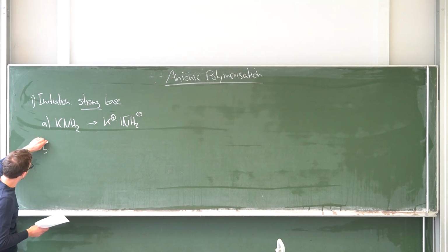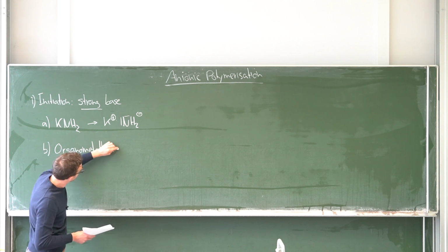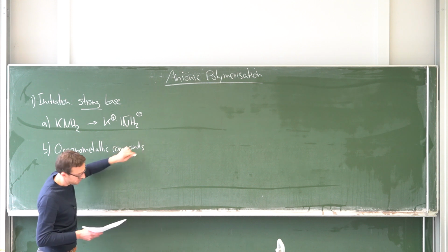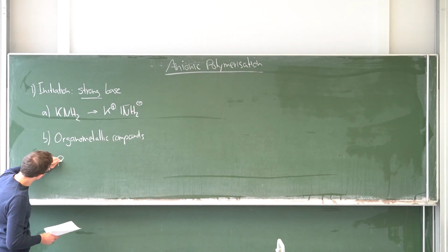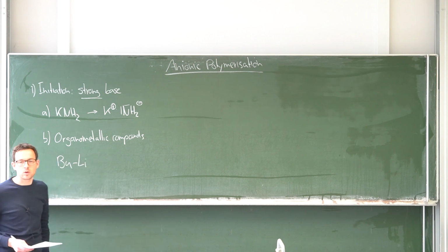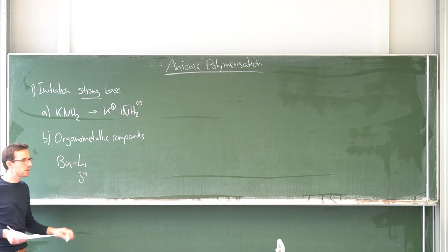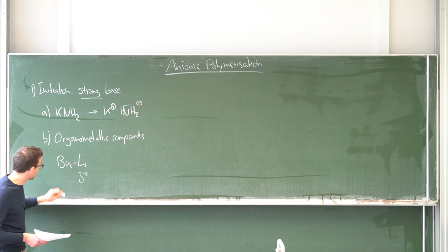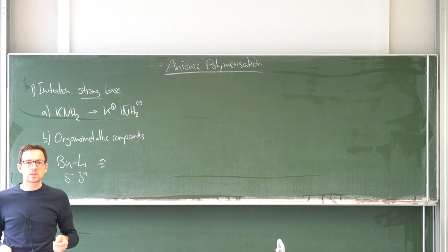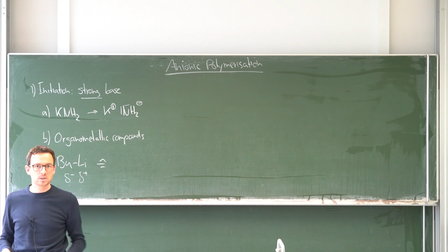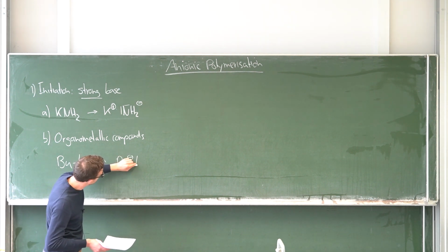The more important one would be, at least in my opinion, organometallic. So an organometallic compound is, for example, butyl lithium. So we know that lithium is the most electropositive element that exists. So this will be very strongly partially positive, meaning that the binding electrons are all shifted to this butyl chain. And matter of fact, the difference is so strong, which is very rare for a carbon component because it's not per se very electronegative. But if you give it the right electropositive partner, it doesn't have any possibility but to accept the binding electrons. So you could almost write this as butyl minus Li plus.